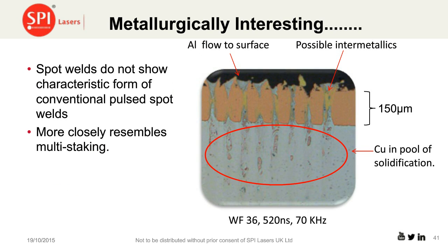What's interesting really is these spot welds are metallurgically very exciting. Being a metallurgist by my first degree, when I first saw this, it really did intrigue me. Because these spot welds do not show the characteristic forms of conventional pulse spot welds, but resemble more closely multi-staking. And here you can see that we're punching into the material through the copper into the aluminium below. And we're melting the aluminium, and it's getting sucked back through the hole that you've just punched to make a solid material meshing between the two materials. And that's quite interesting.